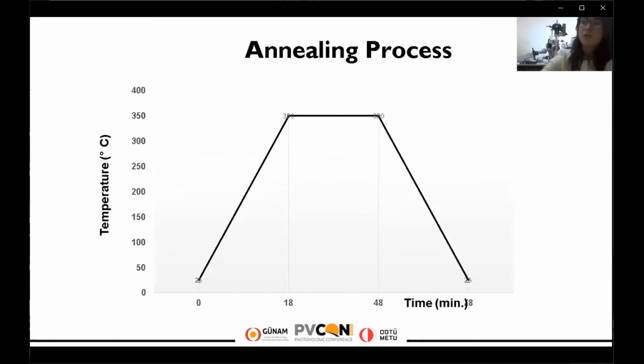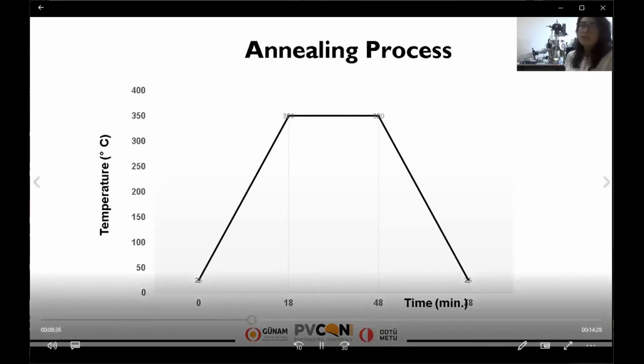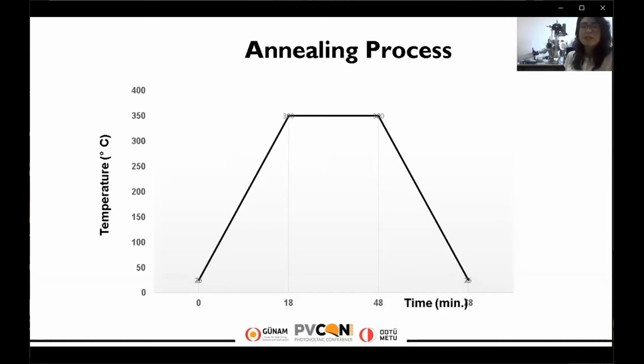Yeah, now we see the annealing process graphic, and why we applied this annealing process. Because of the low mobility of antimony and selenium atoms, the antimony selenide thin films grown at room temperature are amorphous. So we therefore applied heat treatment to all 6 samples, with the same parameters. The samples were annealed at 350 degrees Celsius for 30 minutes under 100 sccm argon gas flow, and the ramping rate was kept stable at 20 degrees Celsius per minute.